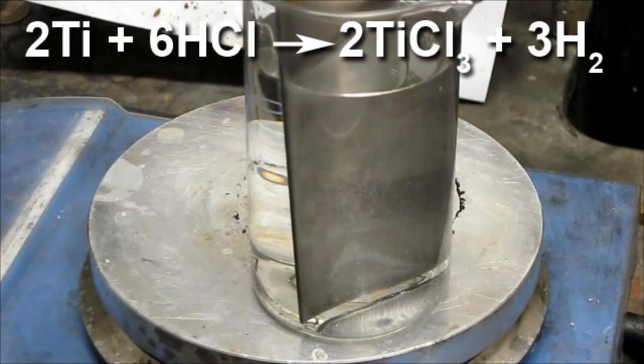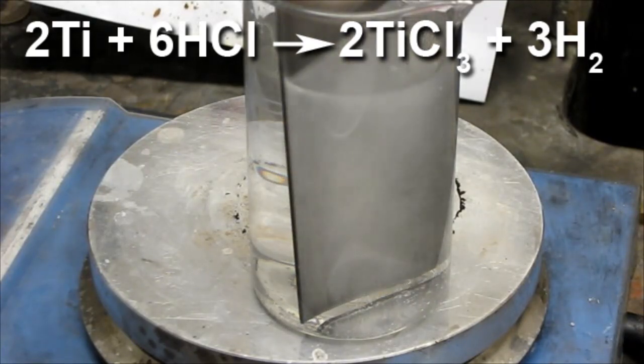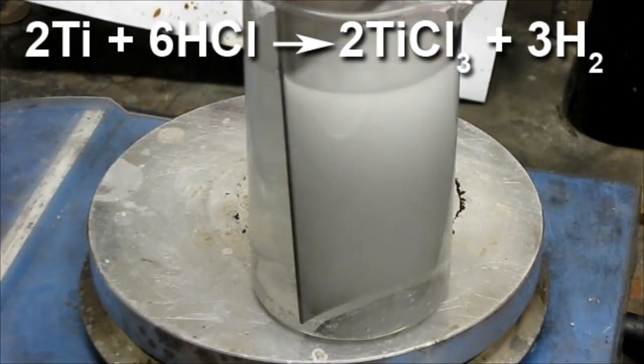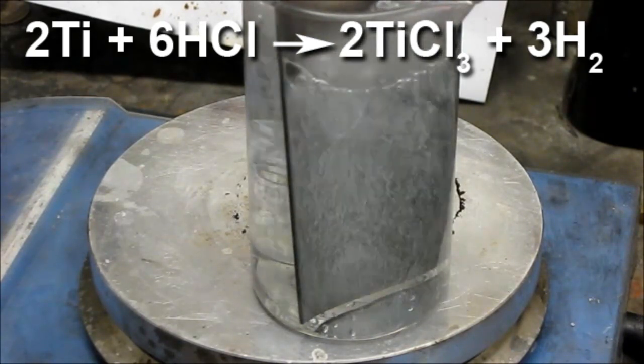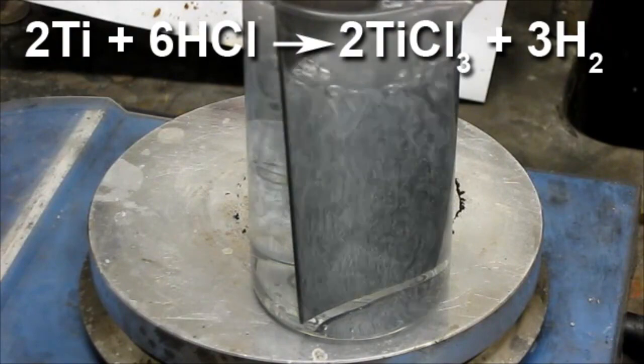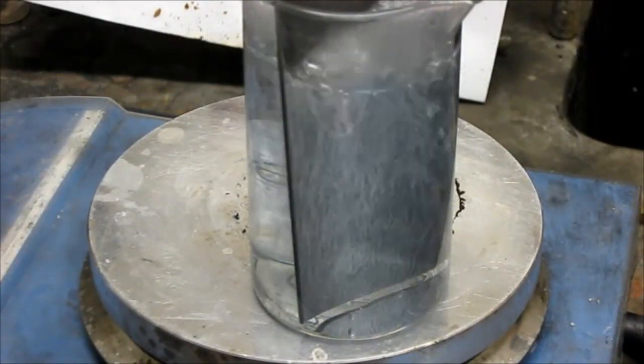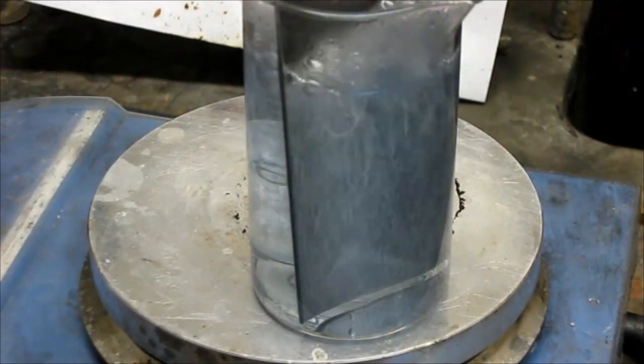Once the titanium oxides are dissolved, the titanium metal should start fizzing as the bare titanium is reacting with the acid to produce hydrogen and titanium trichloride. As this happens, the solution will gradually turn this violet color. When you see this color, the titanium surface is activated and we're ready to start putting those oxides on.